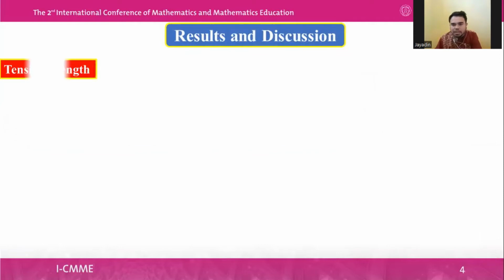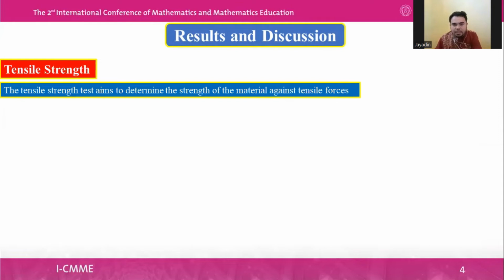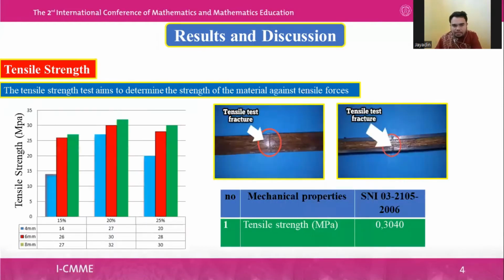Results and discussion. Tensile strength. The tensile strength test aims to determine the strength of the material against tensile forces. The highest tensile strength value is found at the volume fraction of 20% and the core thickness of 8 mm, which is 32 megapascal, while the volume fraction of 15% with a core thickness of 4 mm gets the lowest tensile strength value of 14 megapascal.